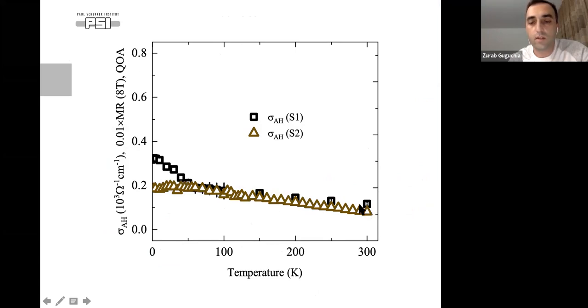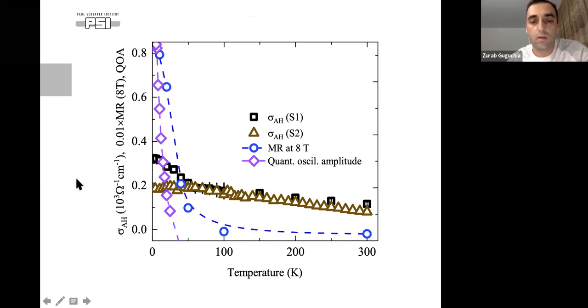The Hall conductivities measured at different samples coincide nicely at high temperature, but their behavior at low temperature is influenced by some transition, which was not known before. And some samples even show higher values. Also, if I plot the magnetoresistance at 8 Tesla, it has a sign change across 100 Kelvin and then a large increase of magnetoresistance at low temperature.